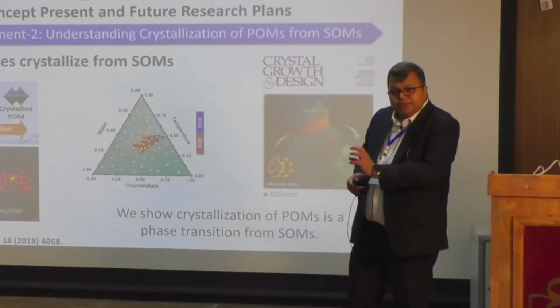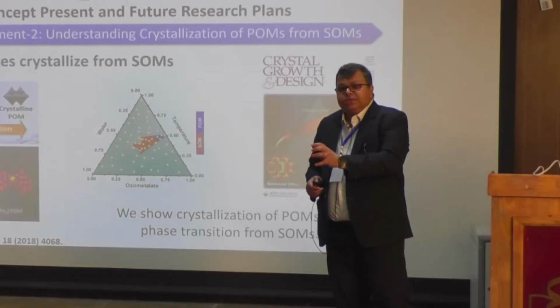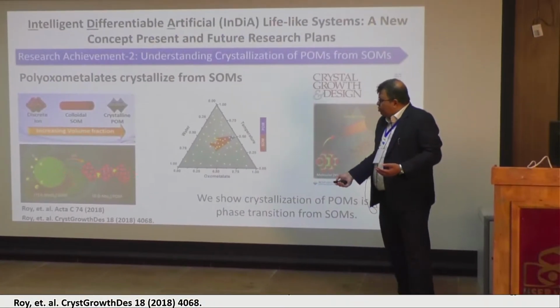And then he was able to show that using this type of system, by changing the pH, it's possible to form MO8 type units, and it also follows exactly the same pathway, meaning you have the molecular anions which, with the change of pH, go into colloidal units, or colloidal SOMs, and then with higher pH it goes to condensation and gets a crystalline domain. And we were also able to get the crystal structure, which is shown here. So we could easily get this type of reaction, right?